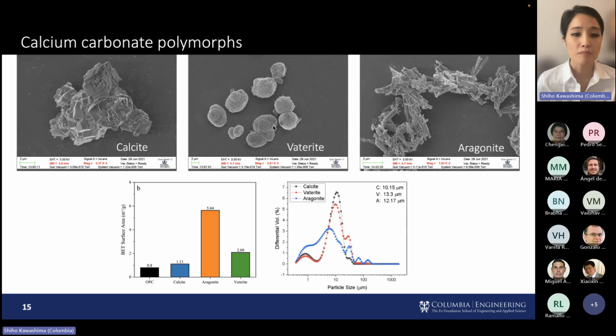But what's cool for us is that through this process we have the opportunity to form these different polymorphs, and they look very different, right? So calcite is cubic, vaterite is spherical and porous, actually, and then aragonite is needle-like. And given the different morphologies, as expected, you see very different values in terms of the BET surface area, where aragonite has the highest, vaterite the second highest, because vaterite is porous and aragonite is needle-like, so high specific surface area and high aspect ratio. And with the particle size distribution as well, in particular, the aragonite has a finer PSD.